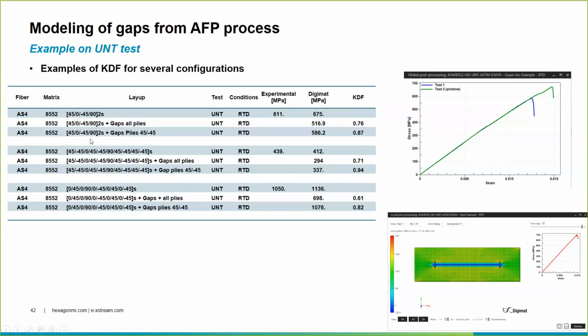But in this configuration, I just insert some gaps on the plies that are oriented at 45 and minus 45. So it means that the plies at 90 and at 0 are unchanged. And in this case, I can also evaluate the effect of the gap.